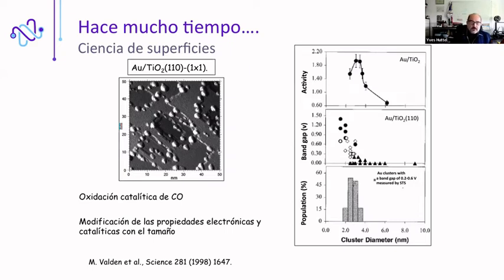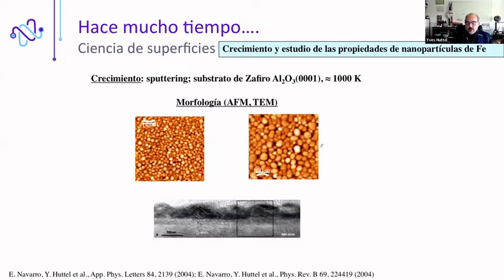So following this kind of studies, in my case, I was studying iron nanoparticles. You can see here in the AFM images, the nanoparticles made of iron. And in this TEM image, you can clearly see the nanoparticles grown on top of a sapphire substrate. But the key point here, in order to get these nanoparticles and not a thin film, was to heat the sapphire substrate at 1,000 Kelvin. And this has a very strong impact, as we will see. But anyway, this temperature was necessary in order to give enough energy to the atoms, in order to push them to migrate and form these nanoparticles we wanted to study.